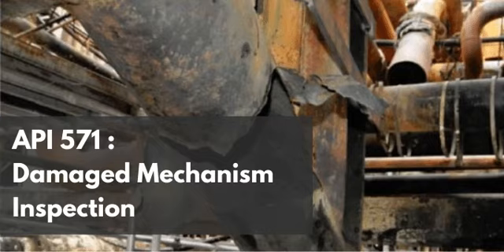Think about it. You are taking a heavy wall 18-inch API 5L grade B pipe, and you're welding in small, highly restrained 1-inch nozzles. Which generates massive localized residual stress. Exactly. Then you are purposefully injecting liquid water directly into a sour gas stream. The water acts as a scrubbing agent, it absorbs the H2S and ammonia, and immediately creates a localized pool of highly buffered, high pH sour water directly on top of the highly stressed nozzle welds. Wow. So if those welds weren't properly stress relieved, cracking is almost an inevitability. It's just a matter of time.